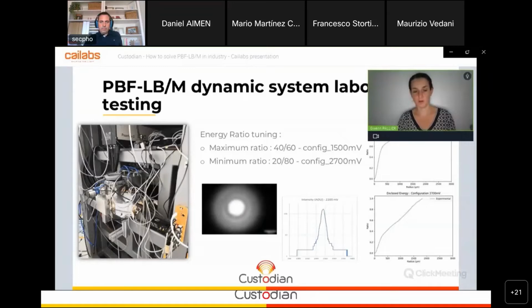And I just want to say that we managed to have the energy ratio tuned from the expected maximum ratio, 40 to 60%, to the minimum ratio, 20 to 80%, in between the first and the second shape. How can you see that? In the image on the right, you can see the enclosed energy. So you will see that, for example, the first shape is pretty small, and you can see that for the same radius, you have much more power.